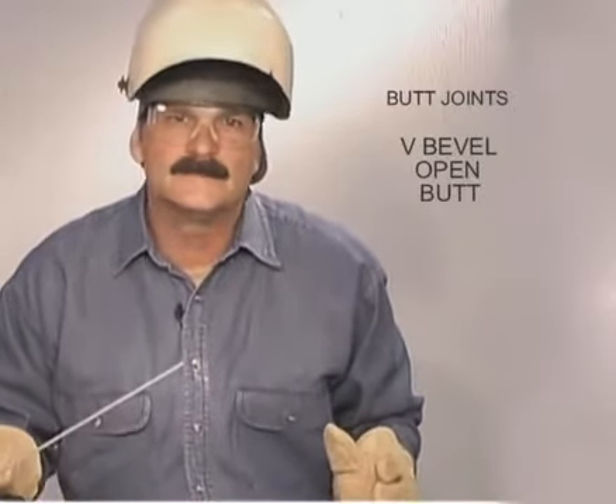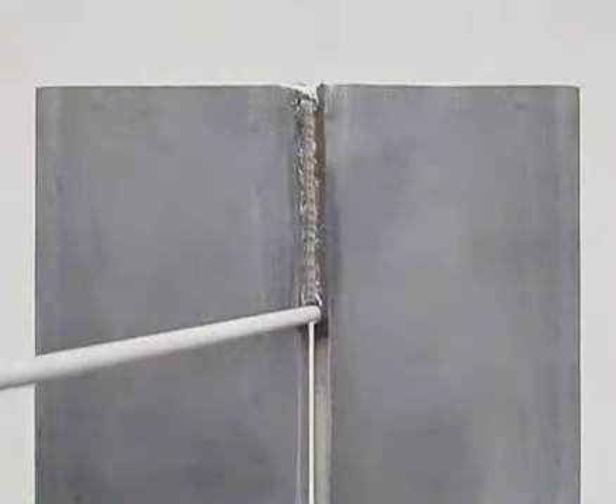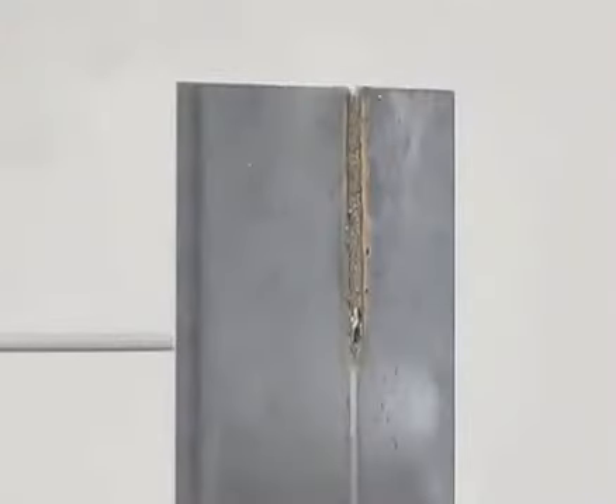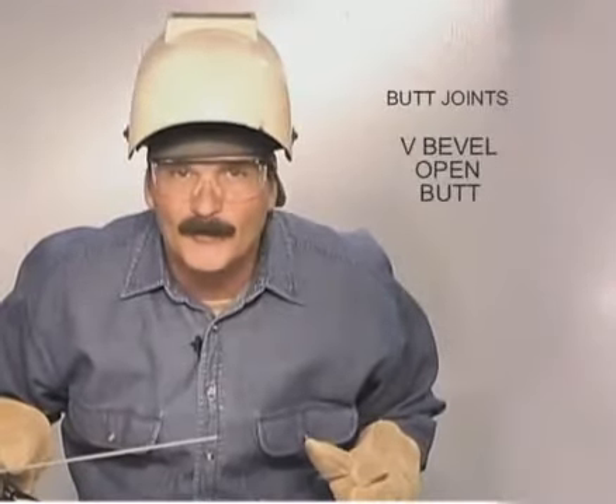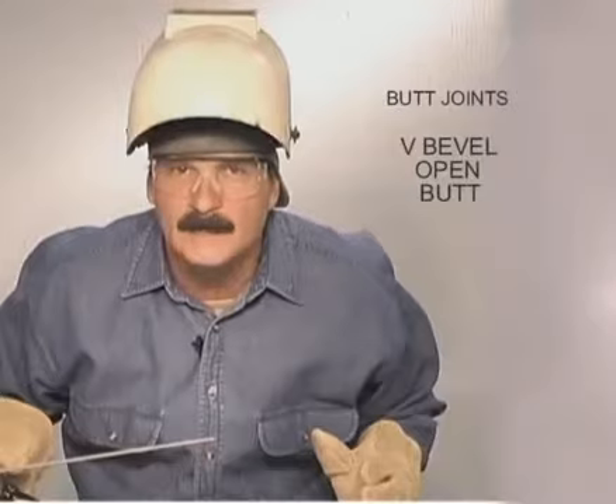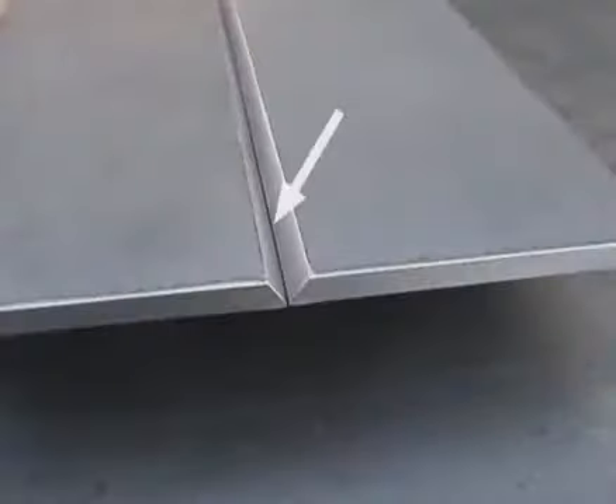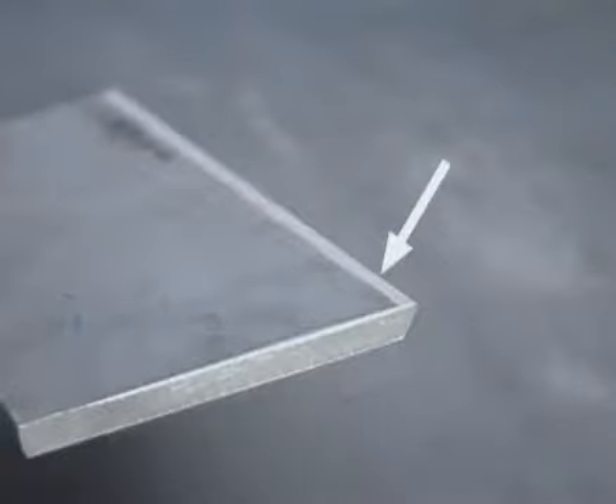The last type of root is in a V-beveled open butt joint. We're going to shove a 60-10 rod deep into the gap and run a weld bead on the back side of the metal. Preparation and fit up are more critical, so take your time getting the metal ready. The edge of the bevel needs to be straight and square. Grind off all the mill scale on the bottom side.